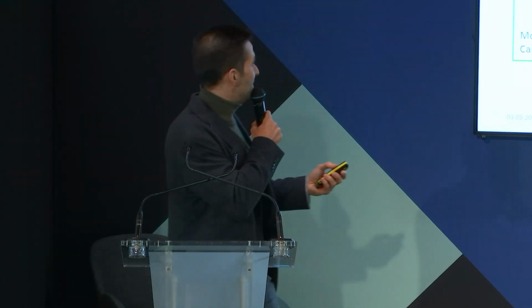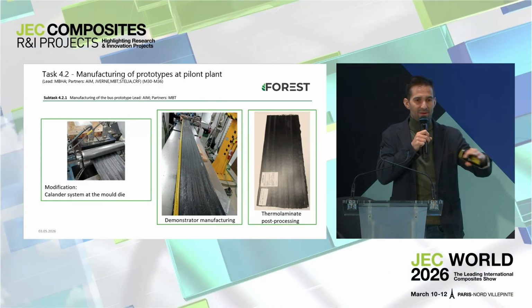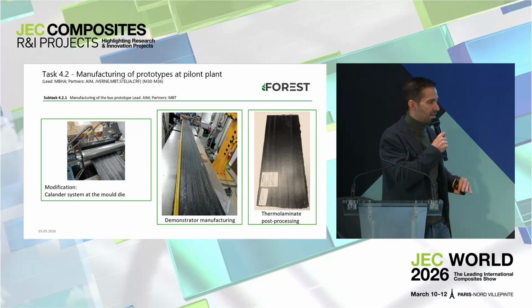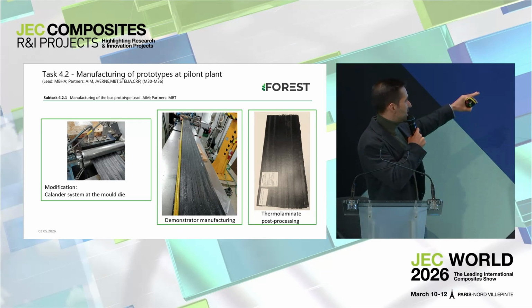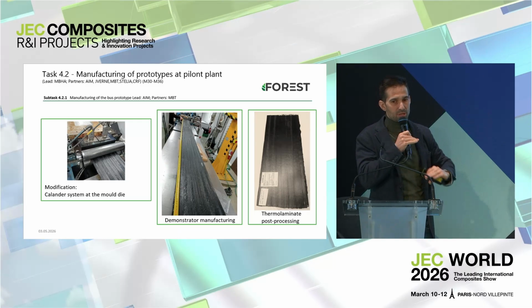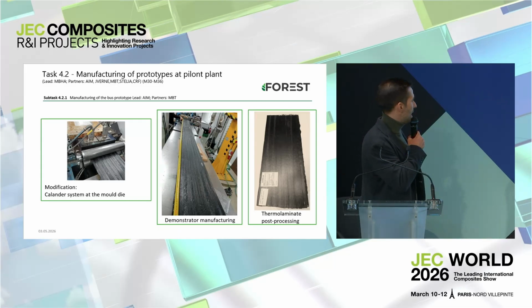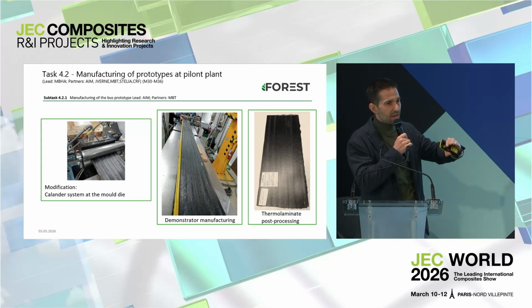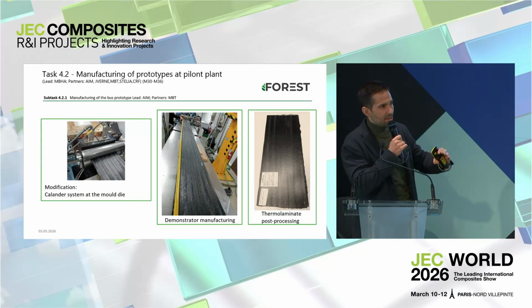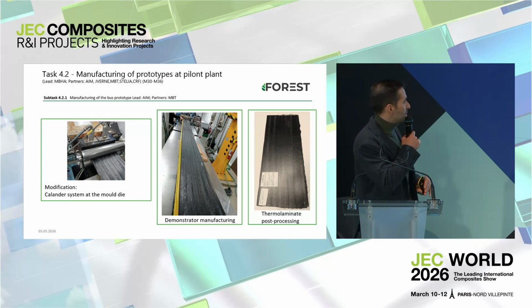Some adaptations, some modifications of the process. The first one: since we noted that there is a relatively rough surface in this profile, in this laminate, we decided to add a calender system at the die of the mold in order to add some more compression and try to make a smoother surface in the laminate. We achieved some, but it's still not the best aspect, since there can be some irregularities, and we might need to improve this part. The second image shows the demonstrator manufacturing, so you see the continuous extraction of the laminate.